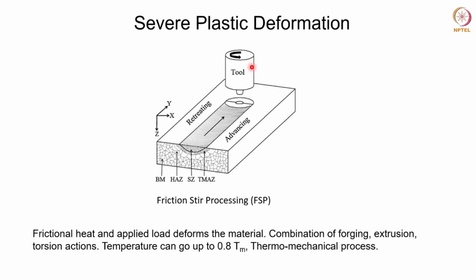So what is done over here is that this pin of the tool is actually plunged into the workpiece, and then a load is also applied simultaneously. A vertical load is applied simultaneously, and the tool is rotated at high speed. So as this pin plunges into the workpiece, the shoulder will touch the workpiece surface, and as the tool is rotated at high speed, with the simultaneous application of the vertical load, a large amount of frictional heat will be generated at the tool workpiece interface, and that will first soften the material.